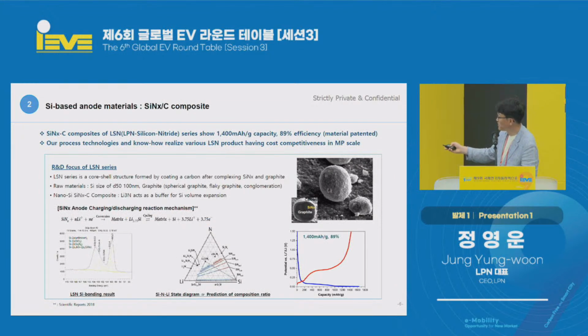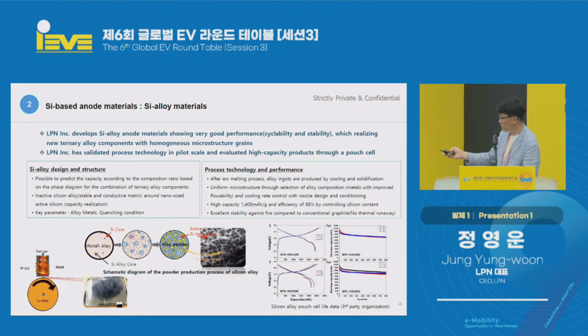In the previous page, you can see silicon has been coated on graphite and carbon isolation. Carbon isolation is a very important step, but without having to do that, we can have the nanosilicon particles surrounding the matrix. So it can be done very fast, and it is produced as a chip. And facility investment is 1/5 of the pulverizing facility with 3 times higher productivity.